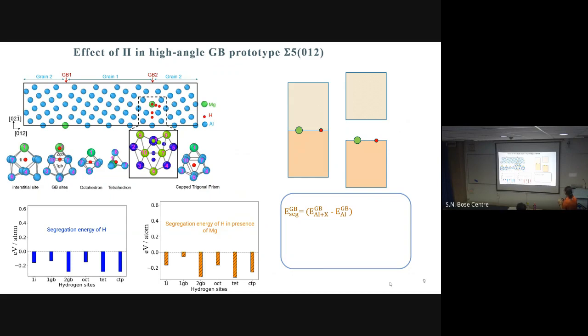I will come to the definition of grain boundary segregation, how I have calculated it. First, I would like you to know that E less than 0 here indicates that the hydrogen atom is happy. The more negative, the happier the hydrogen atom is to sit at the grain boundary instead of the bulk. That is, it will try and migrate to the grain boundary surface. This point is very important.